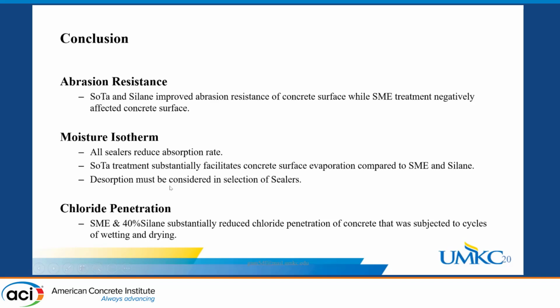And regarding chloride penetration, we can see that soy methyl ester and silane substantially reduced chloride penetration for concrete subjected to cycles of wetting and drying.